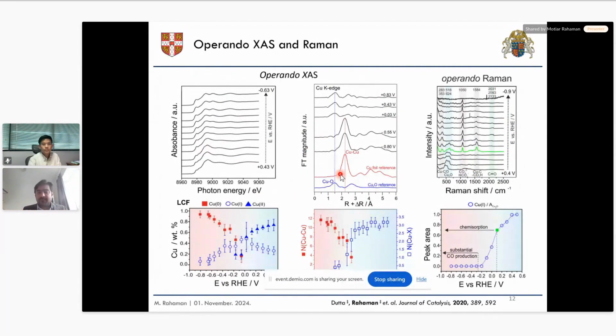So both of these operando spectroscopy studies support that if we take copper oxide as a starting material or as a catalyst, it first gets reduced to metallic copper, and then this oxide derived metallic copper is our active catalyst material for the carbon dioxide conversion process. And this process also formed some ethanol and propanol from carbon dioxide conversion.